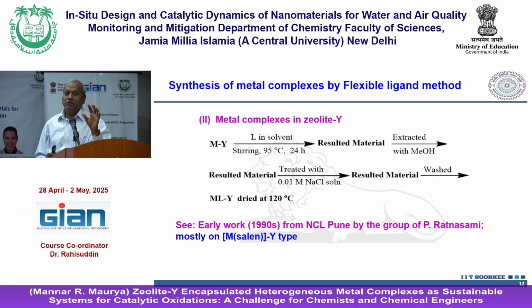So salen was the best because this could melt around 120 degrees very easily. So you can increase the temperature to say 140 and then it becomes a liquid state, and it can enter into the cavity.